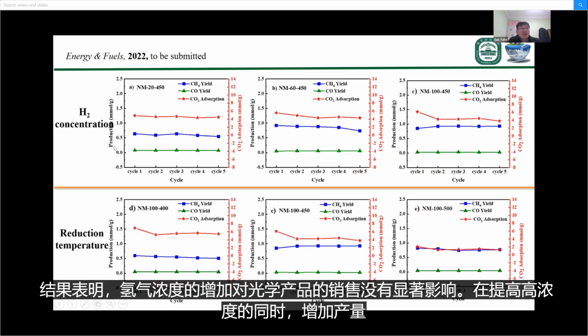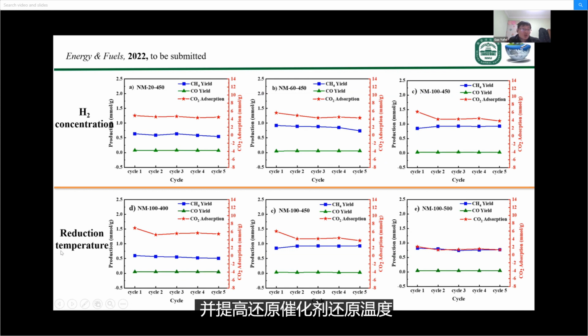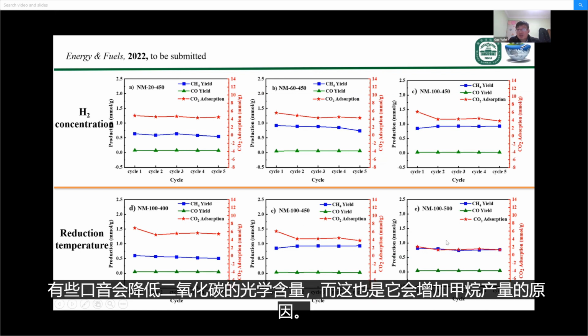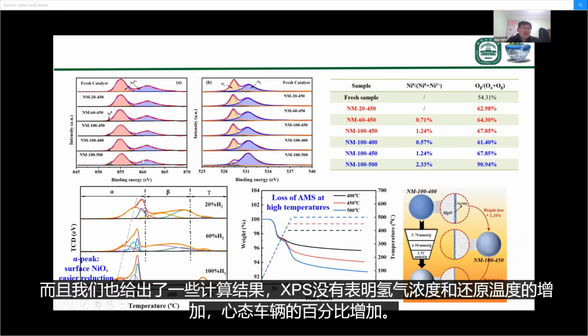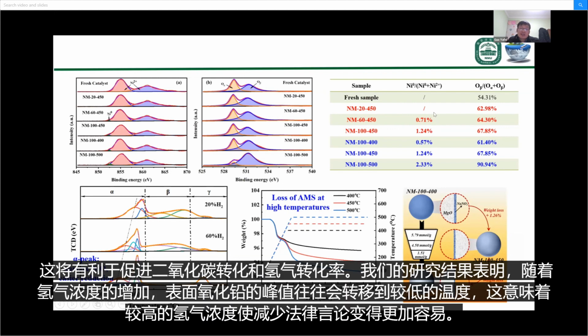And the results show that the increase in hydrogen concentration exerts no significant effect on the CO2 uptake, while it increases the methane yield. And the increase in catalyst reduction temperature to some extent will decrease the CO2 uptake, while it will increase the methane yield. And we have also given some characterization results. The XPS results indicate that with increase in hydrogen concentration and the reduction temperature, the percentage of metallic nickel increases. And this is beneficial for promoting CO2 conversion.